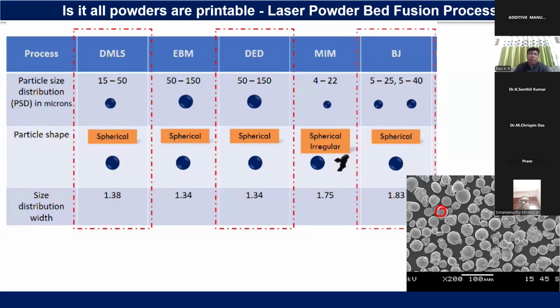If it is spherical, can I use all the powders? What about the size? The size also varies depending on the technology we use. For laser powder bed fusion, it is usually smaller, 15 to 50 micrometer. On the other hand, for DED we use 50 to 150 micrometer, because the bigger the powder, the resolution would be smaller. That we need to understand. But unfortunately, you cannot use smaller size powder for DED, because the powders flow under gravity. Though we use carrier gas, it's not good enough to carry the powder very smoothly to the molten pool. So you need powders of slightly bigger size.